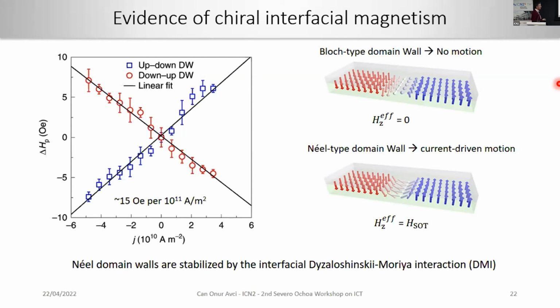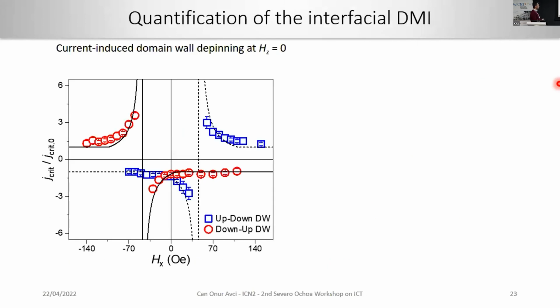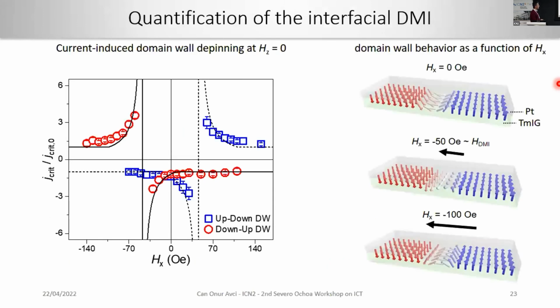So having a chiral interaction and having DMI-stabilized Néel-type domain walls is very important for domain wall motion applications. I will maybe skip the details, because that's basically how we quantified how much effective DMI field was acting on the domain walls, and it turns out to be on the order of tens of Oersted, which is not so much, but enough to make it fully Néel type.